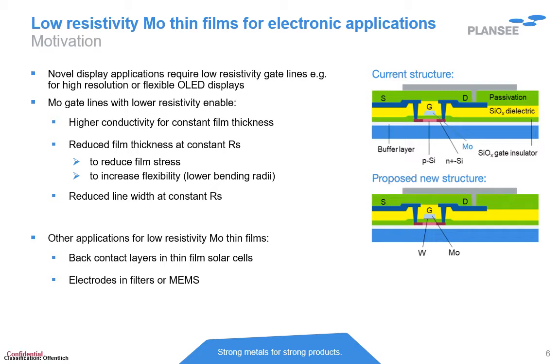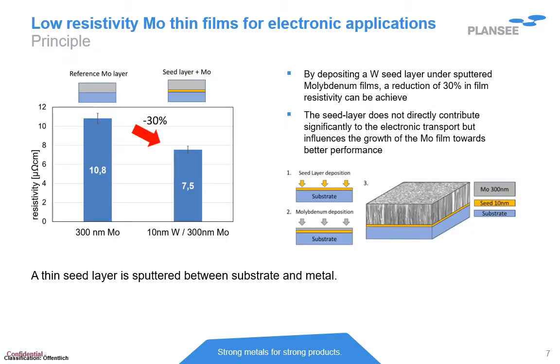This idea of having low resistivity Mo films is not only important for display applications, it could also have benefits for other applications like back contact materials in thin film solar cells, and an increasingly important application as electrodes in filters or MEMS applications. By depositing a tungsten seed layer, for example, under a sputtered molybdenum thin film, it is possible to have a reduction of nearly 30% in thin film resistivity.